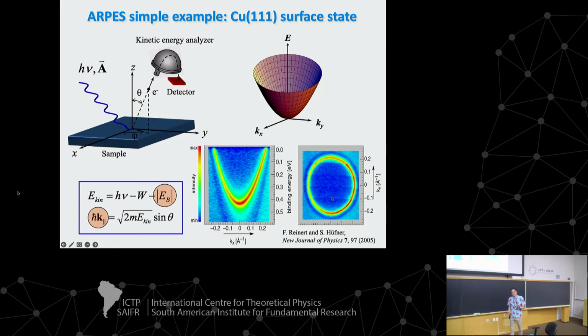Actually, ARPES is much more powerful than just measuring band structure. It can measure the complete spectral function of the system, but for the discussion of today, I will just restrain to band structure. This is an example of a beautiful system that goes well with the single electron picture. This is a surface state at the 111 surface of copper. It is predicted to be a paraboloid of revolution, so a free electron state. And indeed, these are actual measurements.